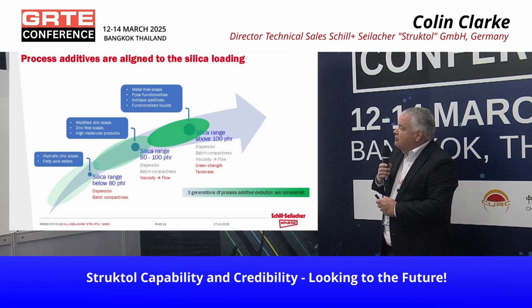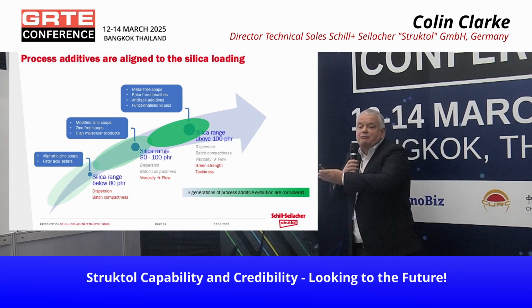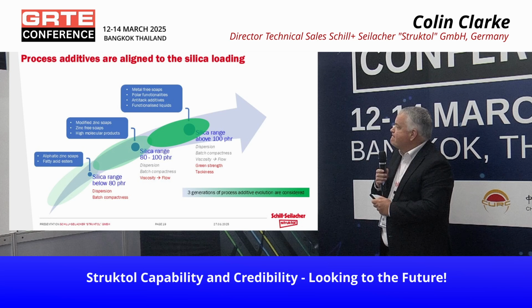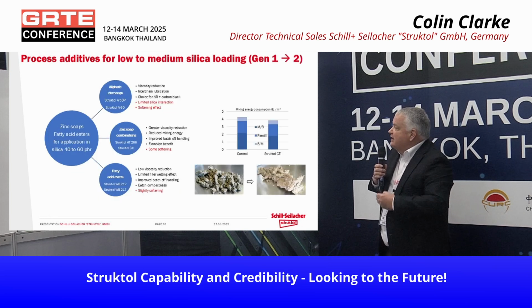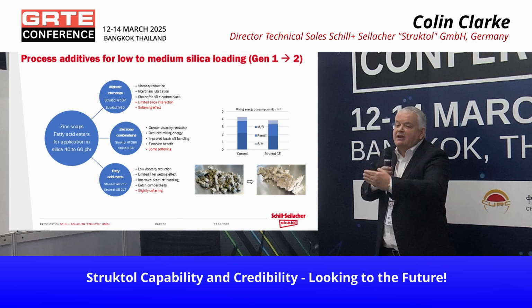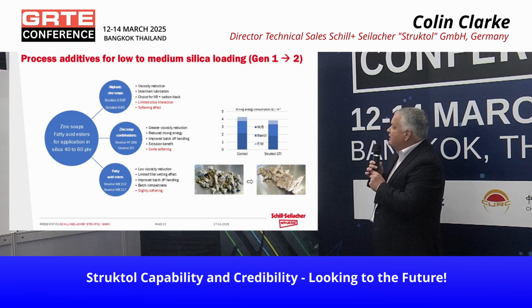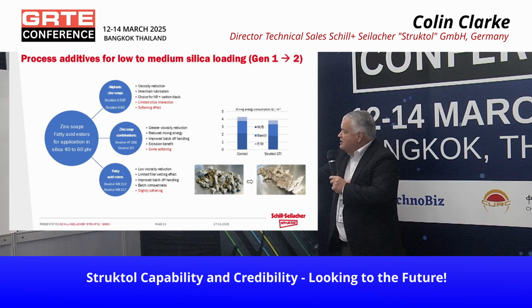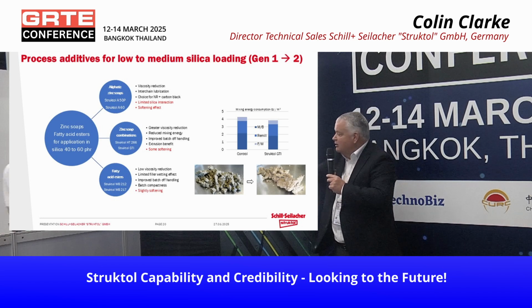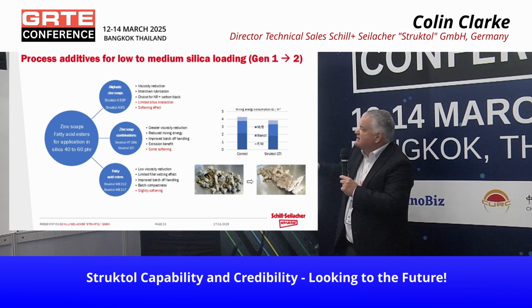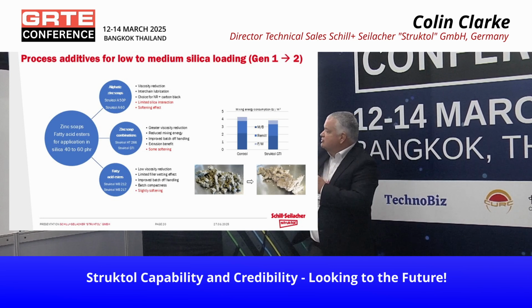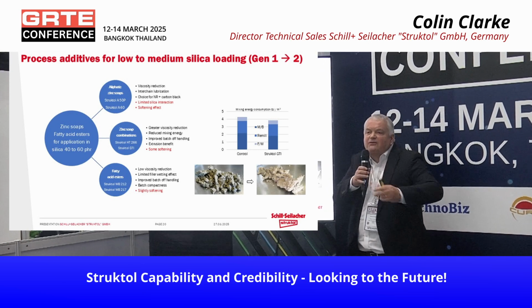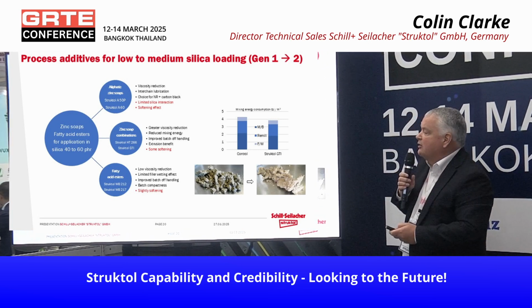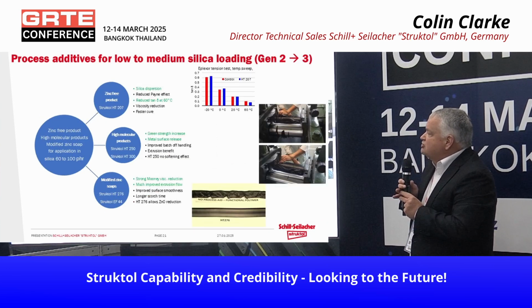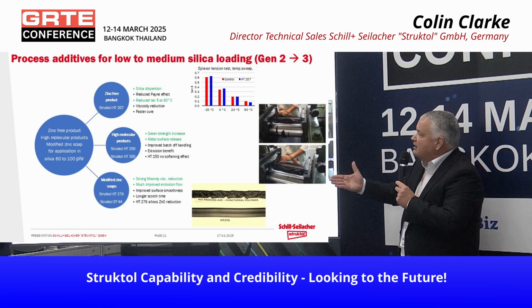So we can really say 3 generations, if you like, of development in tread compounds and associated developments in the process additive technology. So early generation products, very standard materials, so zinc soaps, lubricating, reducing the viscosity, solving things like reducing the energy consumption. Batches that were very crumbly and difficult to handle could become more solid, but more or less very standard products. They gave improvements, but also some limitations, maybe softening effect or not fully satisfying all of the tyre properties, if you like. So later developments, now we could start to see really improvements in the handling of the compound.